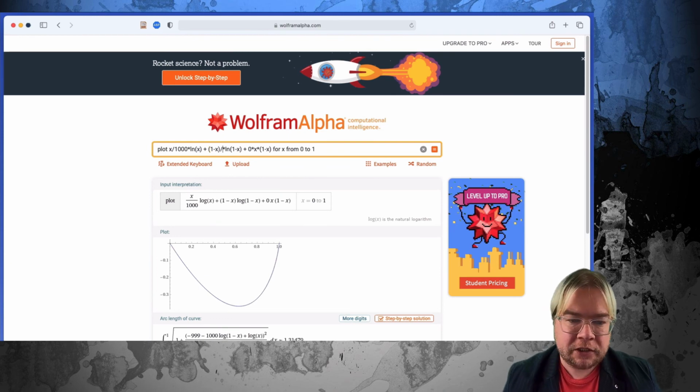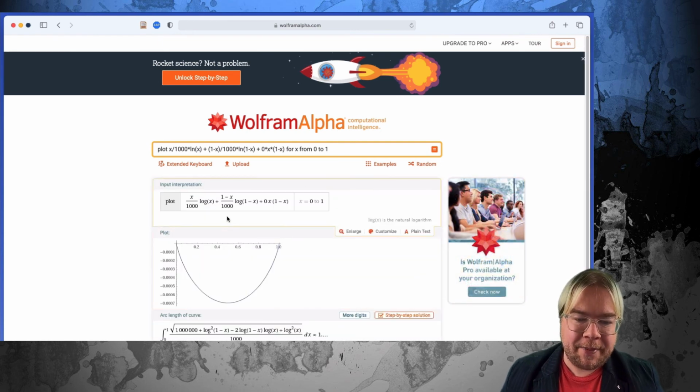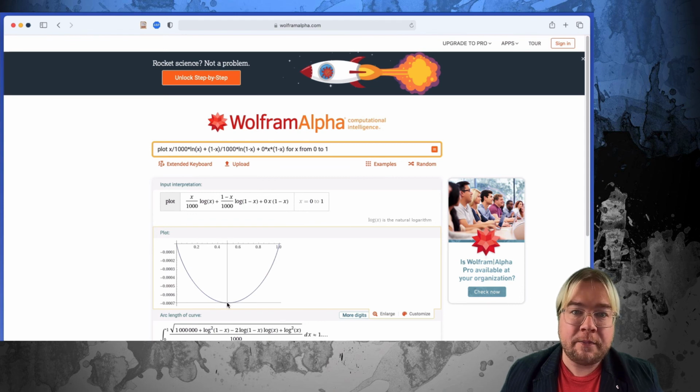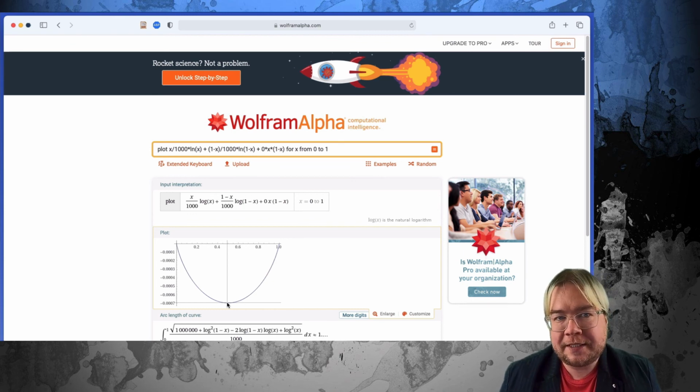We could also look at a blend. So let's set NB also equal to 1,000. And we'll see what that does to the value of the free energy of mixing. So it's symmetric again, but look at the value now. At the minimum of the function, the value is minus 0.00069. So it's practically 0 just by having two polymers together. So this is what I was saying last time. The entropy of mixing scales as 1 over the molecular weight. And so you can see for this symmetric blend of polymers, they both have the same molecular weight, that the contribution to mixing just due to entropy isn't very big.